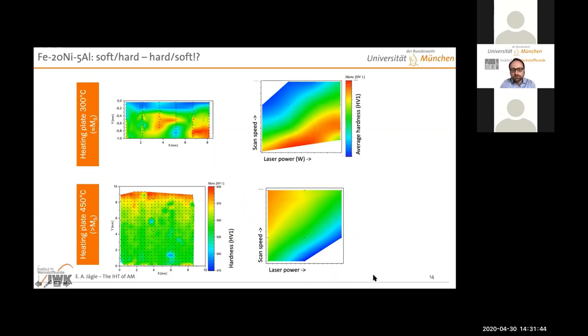And to confuse us even more, if you just look at the hardness in the middle of the specimen and plot this as a function of processing parameters, you have a complete reversal. For the low base plate temperature below MS, with a low energy input, so high scanning speed and low power, that gives you a low hardness. Down here at high base plate preheating, it's just the opposite. A high scanning speed at a low power gives you a high hardness.